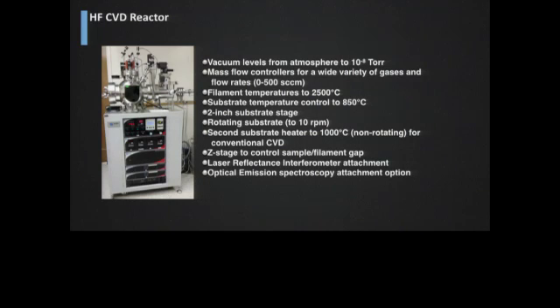One thing that's very, very important is the spacing between the filaments and the actual platform where the wafer sits, a susceptor. And so we can adjust that. That's the Z stage, so we can adjust the height. We've also added some diagnostics to give us some idea of what's taking place inside the reactor as we grow. One of the earliest things that we added was a laser interferometer attachment, so we can actually measure in situ the thickness of the layer as we grow it.